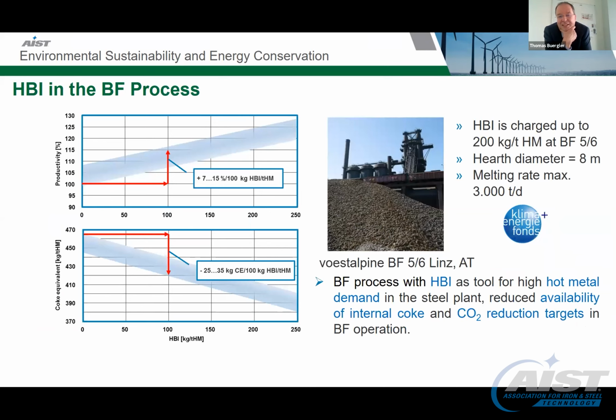Yeah, first we started with the HBI from Texas in our blast furnace operation. We are able to charge up to 200 kilograms HBI per ton of hot metal, and with this you can reduce the CO2 emissions of the blast furnace by approximately 30 kilograms per coke equivalent by charging 100 kilograms of HBI. This is not a new experience. This is well known for several decades from other companies, but the use of HBI in the blast furnace process is the first step to reduce the CO2 emissions of the classically integrated process.